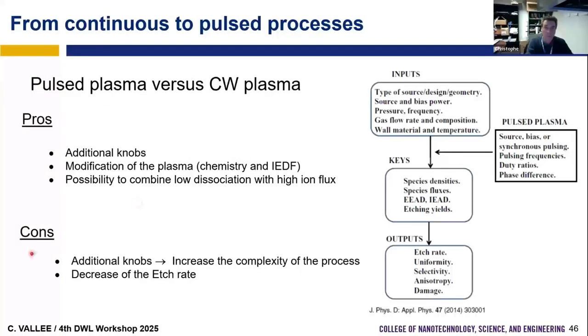So the benefit of pulsing the plasma is that you have an additional knob. You can modify the plasma chemistry and ion energy and distribution with time, which you could not before. So now you can modify the time. And now you can combine low dissociation and high ionic flux. But since you have more parameters, you increase the complexity of the process. And regarding throughput, if you pulse, you have less time on, so less time of RIE, energetic ions with radicals, so usually you observe a decrease of the etching rate.